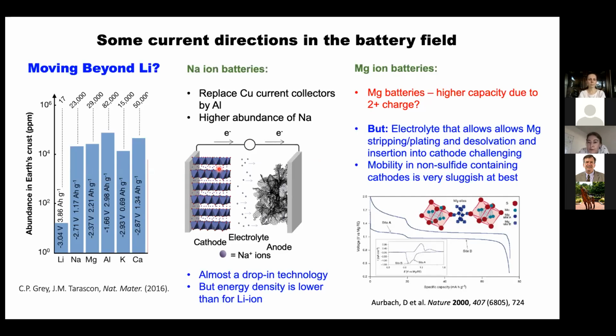But not only the problem of mobility, one of the biggest challenges is actually to be able to strip and plate magnesium, because it's a 2+ cation. And so the best materials to date are these Chevrel phases, these molybdenum sulfides done by Doron Aurbach, and those work because the sulfur is squishy and you get reasonably low activation barriers for transport.